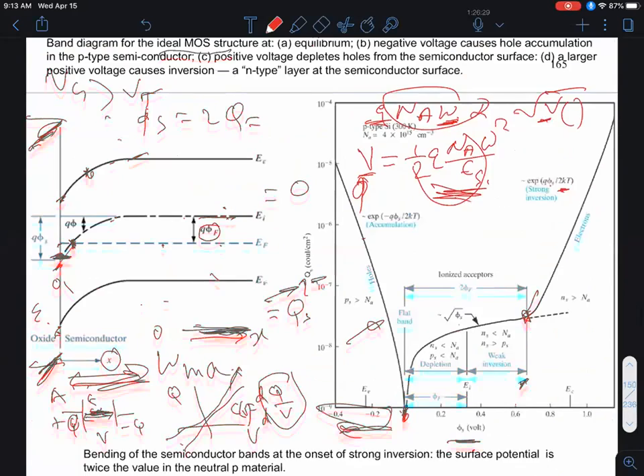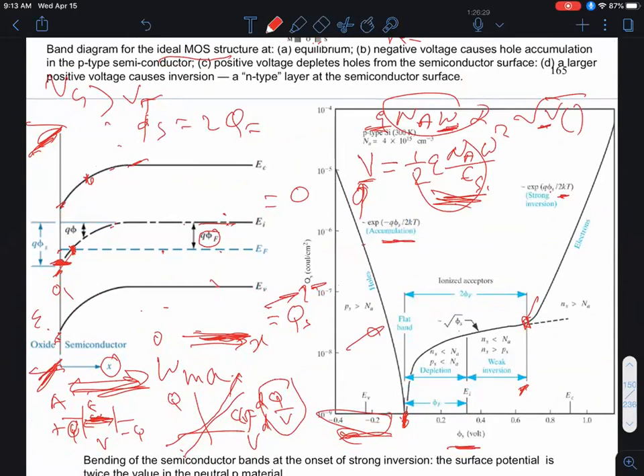which is what was graphed out here, right? And you can see clearly that initially under flat band conditions, where there's no band bending, of course, the charge has to be 0, space charge neutrality. For negative surface potential, the convention here chosen is the bands are bending upwards. That's my accumulation. I get a carrier concentration which changes exponentially with surface potential divided by 2 kT, because phi s is a potential right at the surface. You have to average over this whole region, and that introduces a factor of 2.